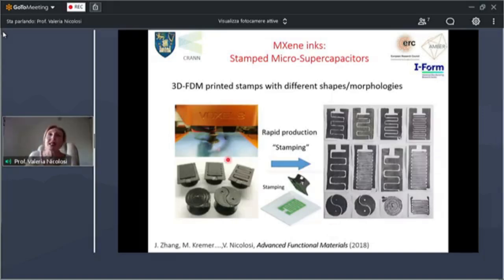So we built this methodology where we can print by 3D printing, fused deposition modeling, just conventional stamps, and you can give the geometry and the design that you want. When we do supercaps, we love interdigitated structures. Those are these stamps here, or you can be a little bit more fantastical and just open up your freedom in your mind. And basically, you can make the stamps of the shape you like. Once you've made the stamp, you only need to dip the stamp into your ink, and you can stamp away your device on any substrate you like. In this particular case here, we printed onto paper.